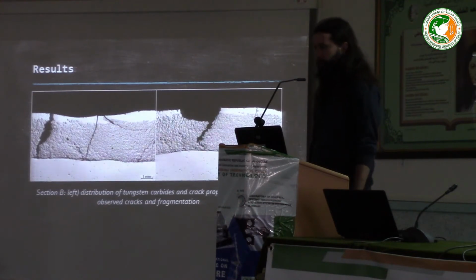Now this is section B, where the presence of tungsten carbides is far more significant, as can be seen by the black dots, and also you can see that there are significantly more cracks and micro cracks here, and that even in some extreme cases crack fragmentation has occurred, so there is a large part of the welded layer missing, like in the picture to the right. This can lead to much quicker loss of material and is something that should be avoided and can be prevented to an extent by applying an intermediate buffer layer, which would serve as an elastic transition between the welded layer and the parent material.